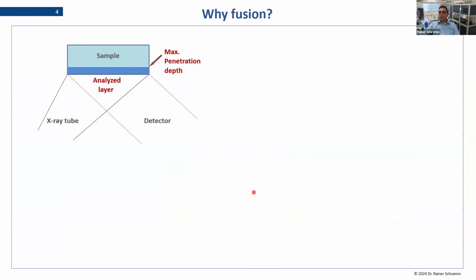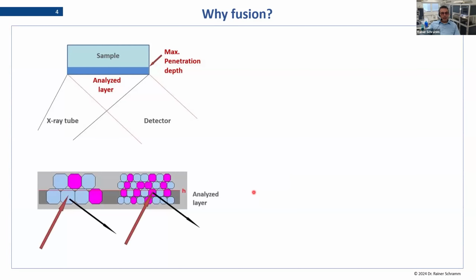It has all to do with the penetration depth of the X-ray technology into our sample. It means how deep we analyze our sample. And there we have the difference between a loose powder or press pellet and a fusion: if we just have a powder in a sample cup or in a press pellet, we have single particles lying in our analyzed sample. And the X-rays, which come from underneath, just see the particles which are lying on the measuring side and not particles which are deeper in the sample. And this depends on the element you are analyzing.